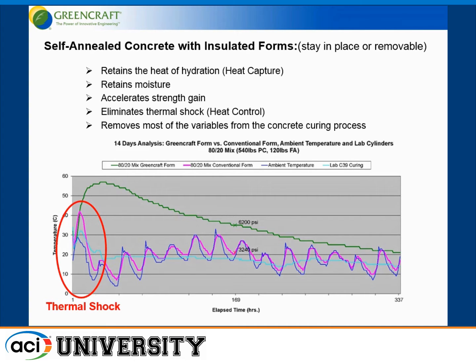So we can retain the heat of hydration, retain the moisture, and then all sorts of things happen. We climb to a far greater temperature, we sustain that temperature for a while, and then we gradually lose the heat, in this case about 1 Celsius degree a day. At 7 days, we get 6,200 PSI with the self-annealed concrete, while the conventionally formed concrete is at 3,200 psi. Basically, we eliminate the thermal shock and remove most of the variables from the concrete curing process.